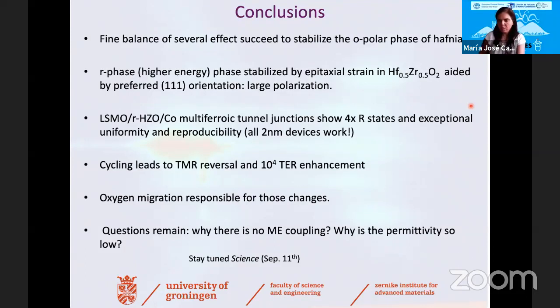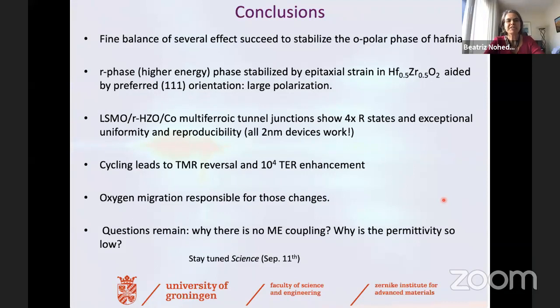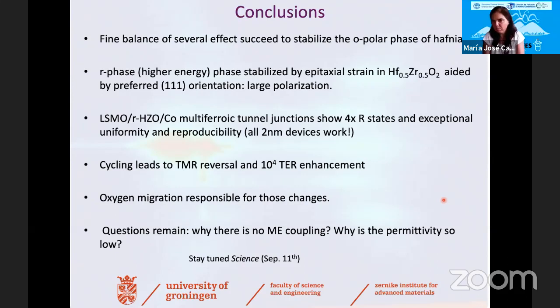Okay. So while we wait for more questions, just a question that maybe it's a little naive. You have ferroelectricity in very thin layers. Does it mean also that you can draw very small ferroelectric domains on the surface compared to other ferroelectrics? Well, artificially you can choose the size of your domains if the material is stable. But indeed, the natural domains that are formed in the material in order to avoid depolarization fields are correlated to the thickness of the material. So if you have a very thin film, the domains that will form naturally to avoid depolarization fields will also be very small. Okay. So you can actually get very small domains, so very large miniaturization. Yeah, that's true.